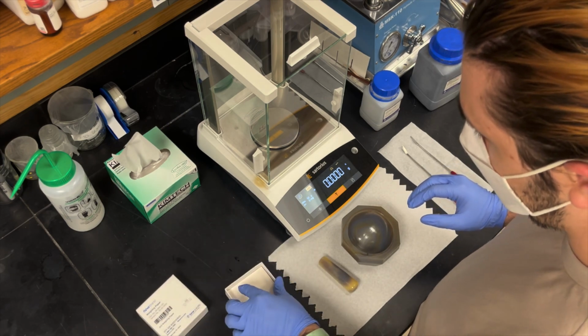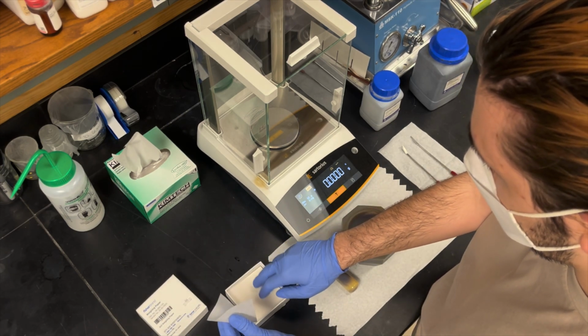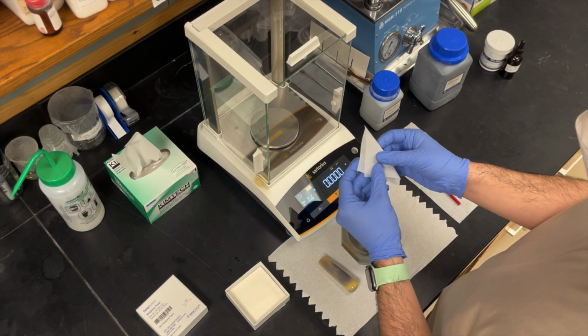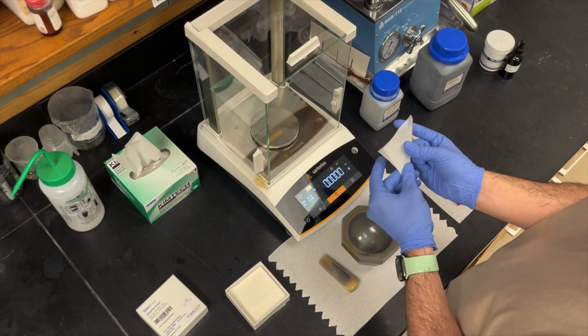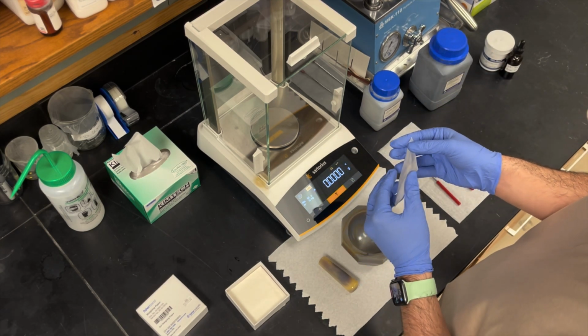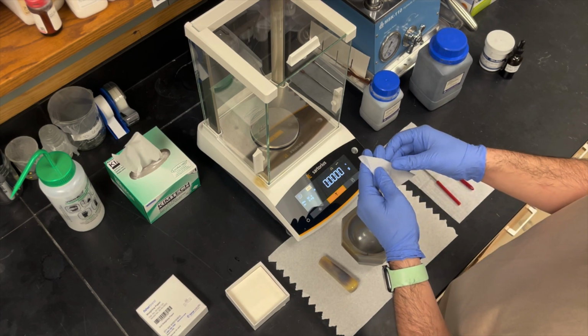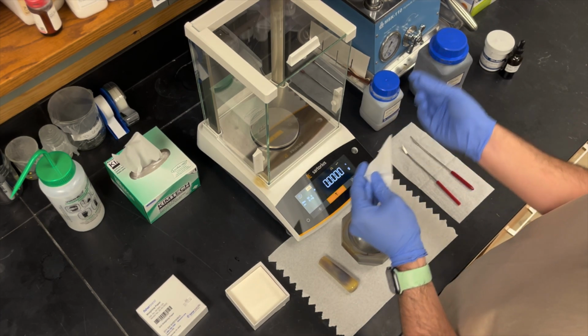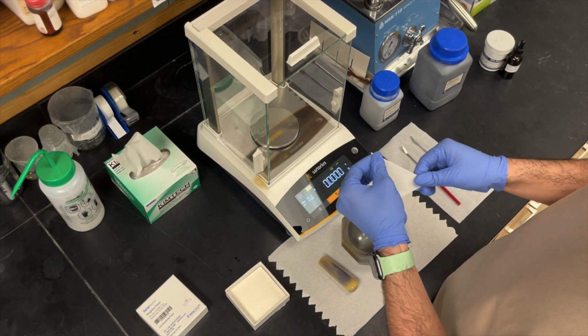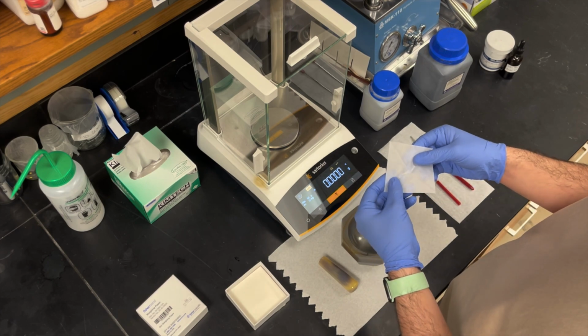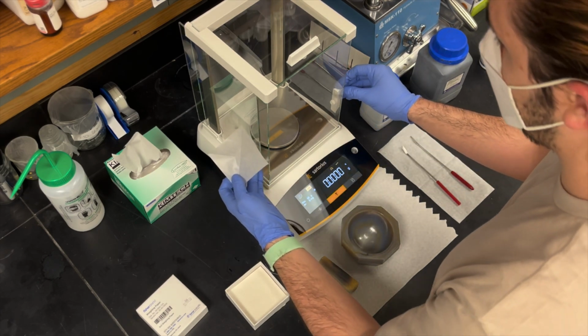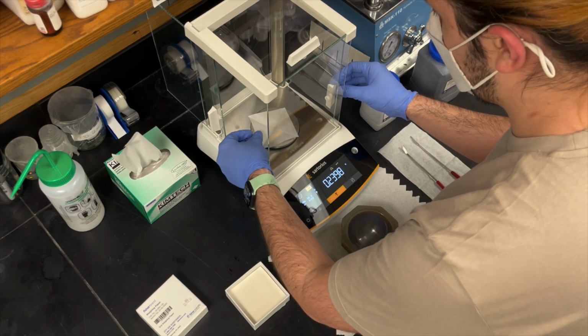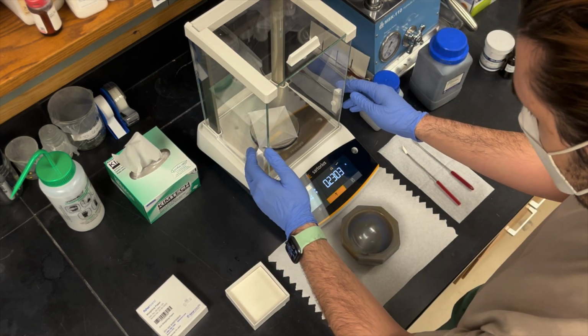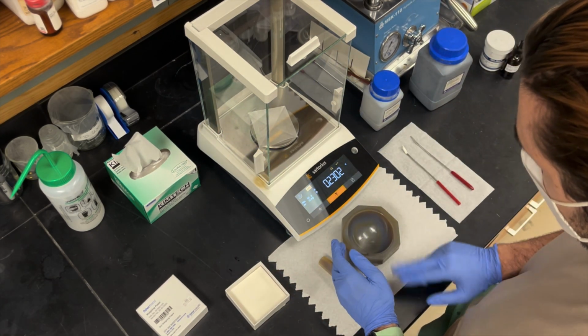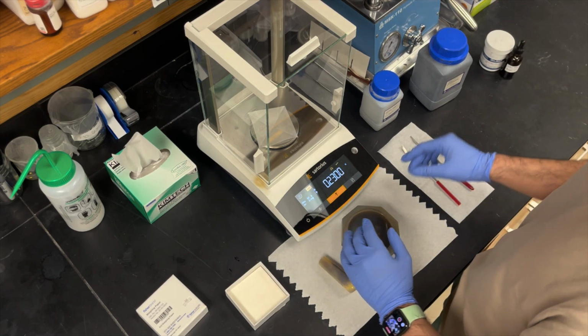Current research suggests that these materials should be combined in a ratio of 80% active material, the NCM or the graphite, 10% carbon black, and 10% PVDF. As a little trick, I've folded the white paper diagonally twice so as to make it easy to transfer the powders from the white paper into the mortar.